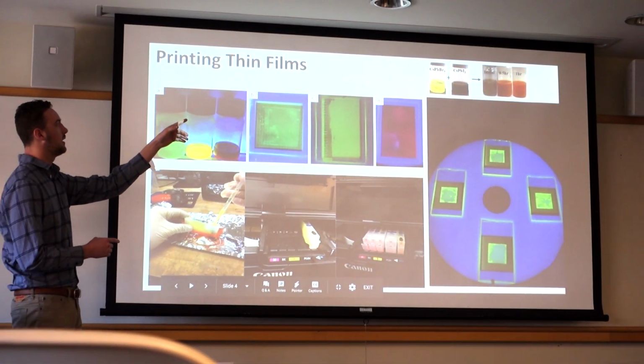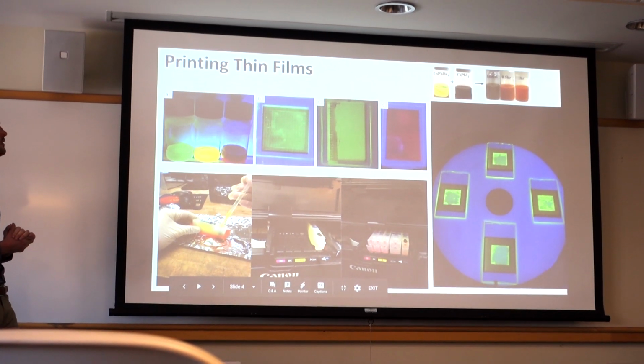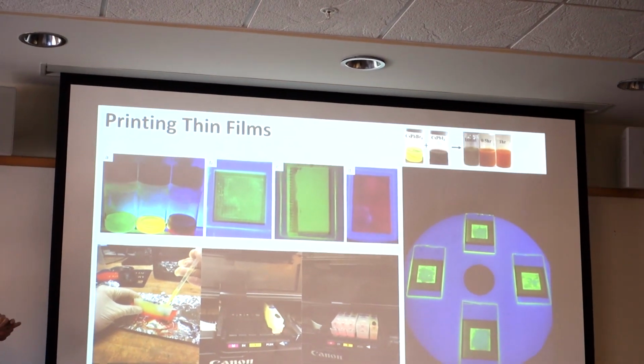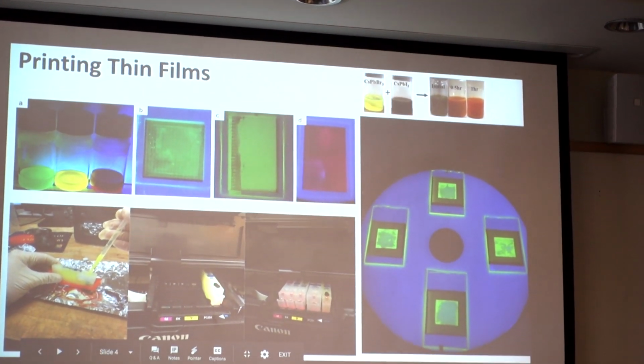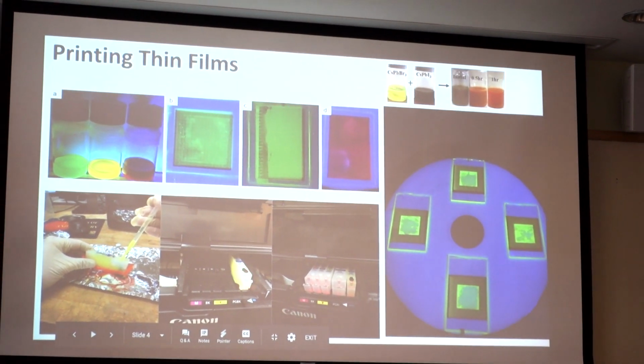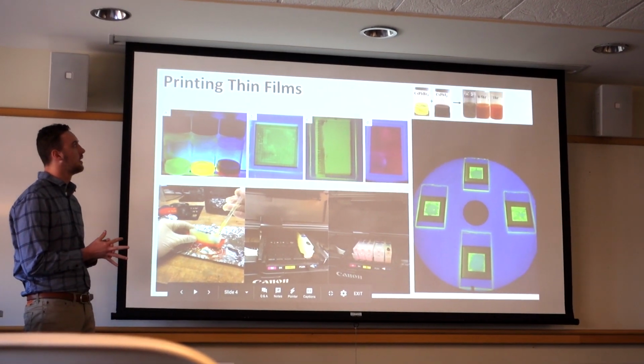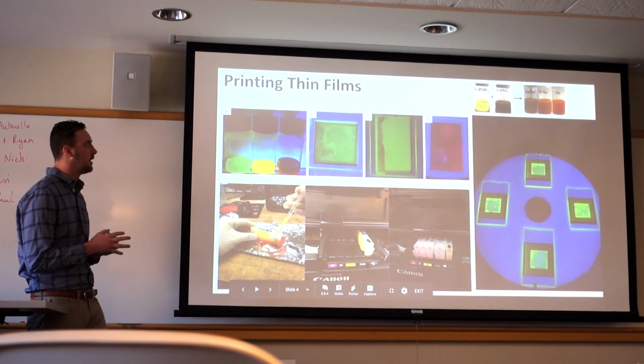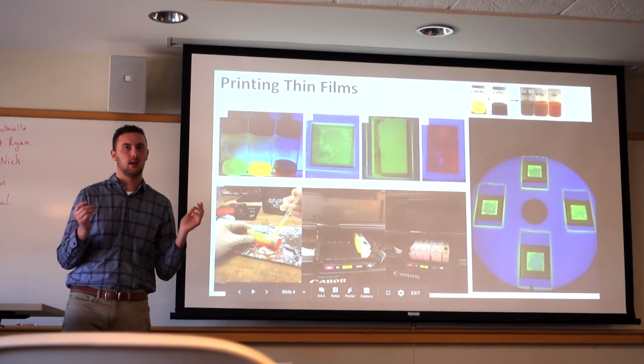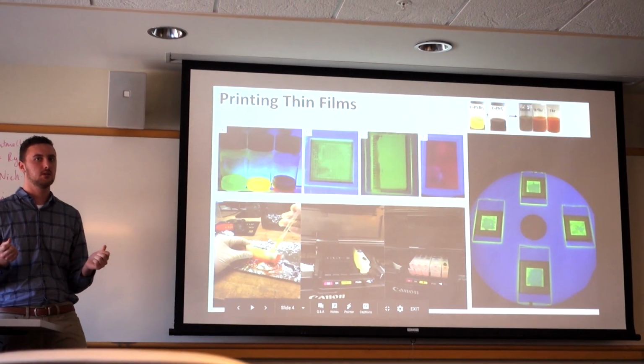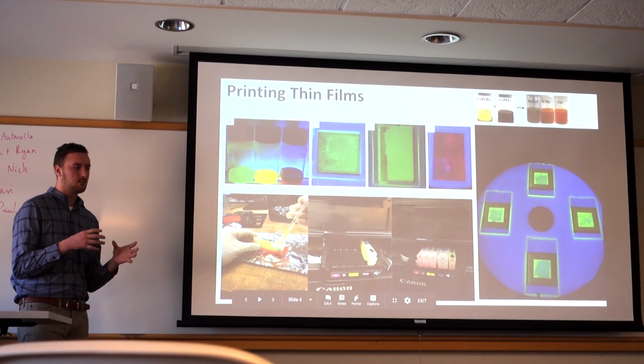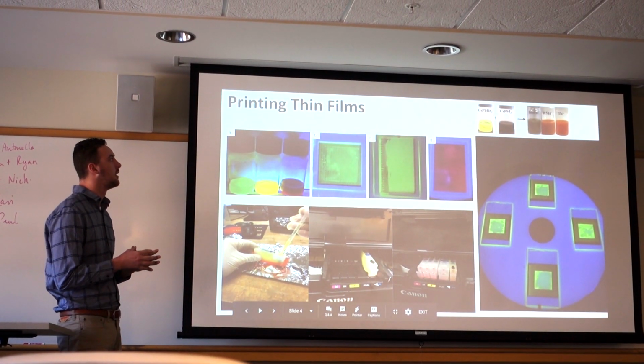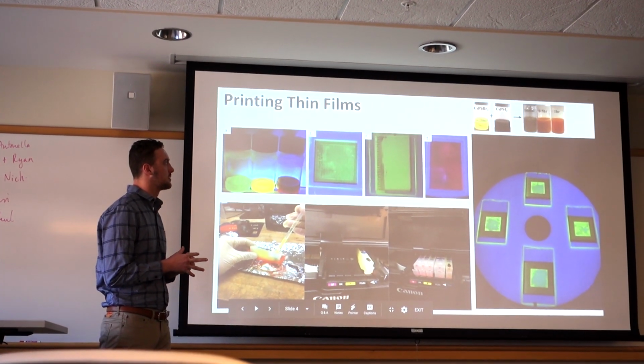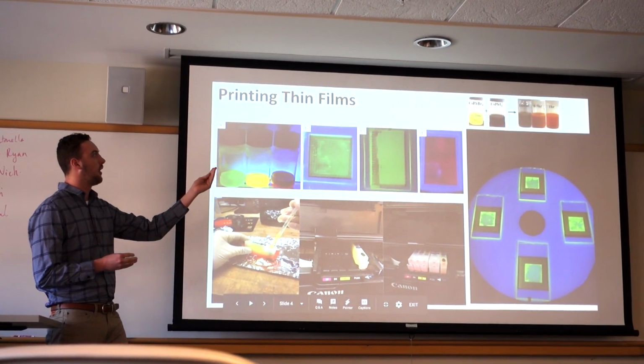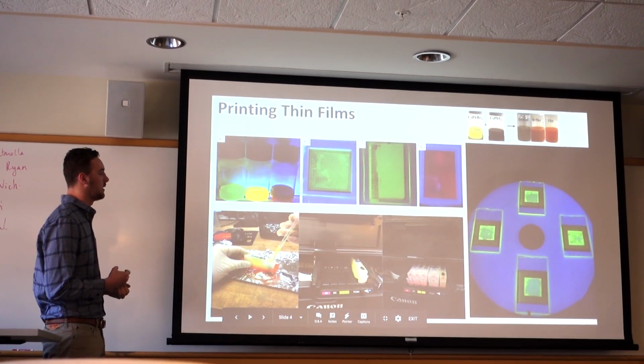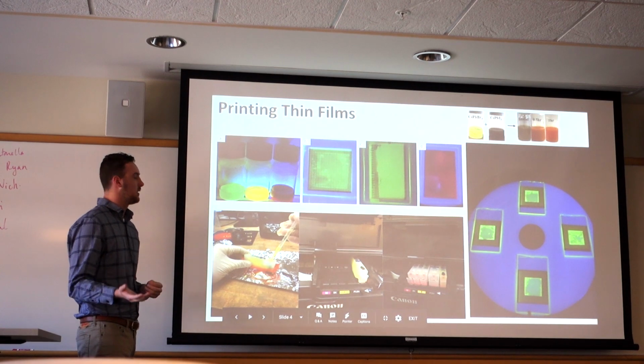Up in the top corner, that is the direct mixing process we use to create the mixed perovskite. So we take a 50-50 equal mass mixture of the two pure perovskites and directly mix them together. And then over time, the halides in the solution mix and combine with each other in unequal amounts. And after some time, we get this orange solution, which is the mixed perovskite alloyed together. And we will see that a little bit later.